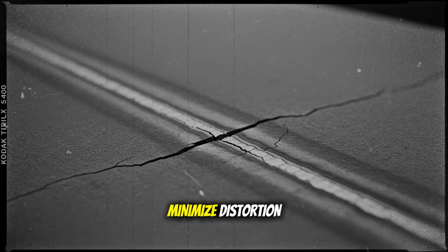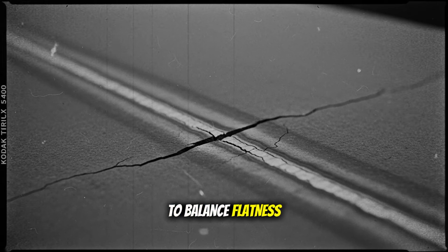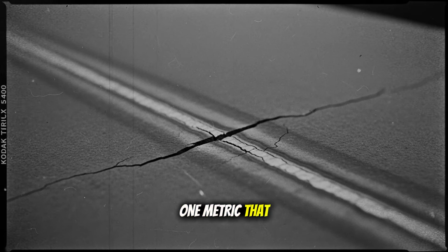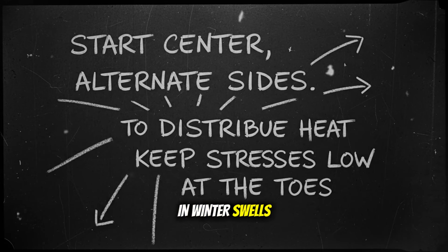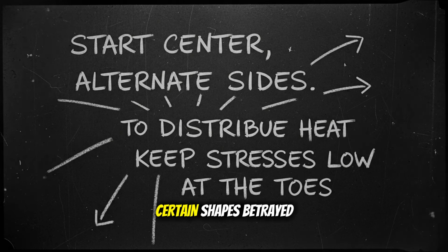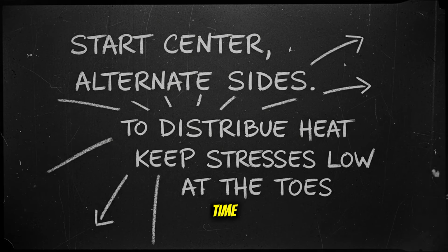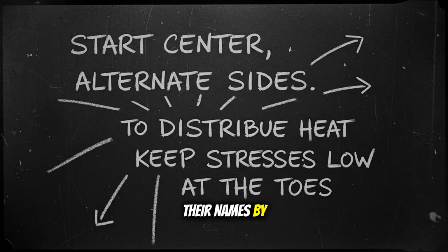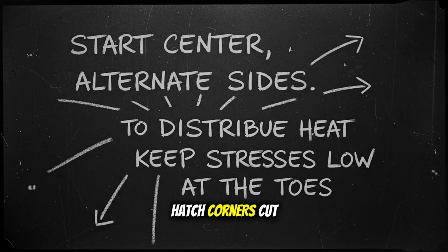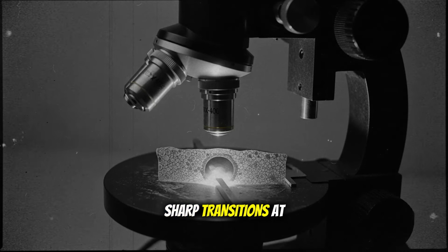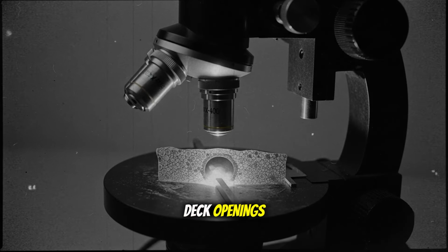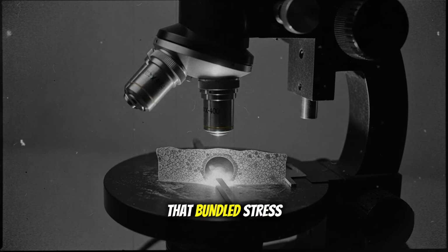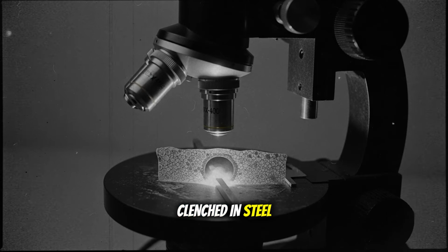Even choices that minimize distortion did not always minimize residual stress, a trade-off that forced planners to balance flatness, locked-in tension, and fatigue life instead of chasing one metric that could betray them in winter swells. On deck plans, certain shapes betrayed the ship every time, and welders knew their names by where the cracks began: hatch corners cut square for speed, sharp transitions at gun tubs or deck openings, and intersecting seams that bundled stress like a fist clenched in steel.